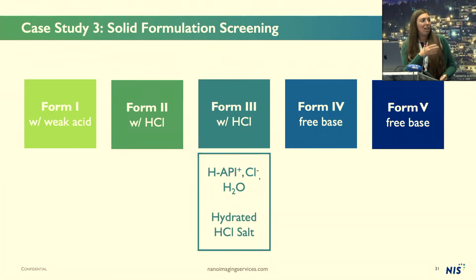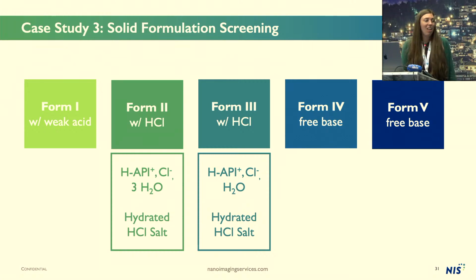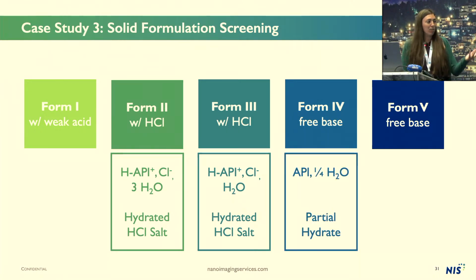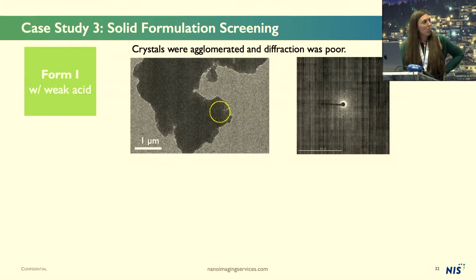So first, we solved a structure of form 3. This was pretty easy, straightforward. It turned out it was a hydrated HCl salt, so that was kind of interesting. Form 2 turned out to also be a hydrated HCl salt, but there was more water content. Then we looked at the free base, found it was a partial hydrate, solved that structure. And then on to form 1.